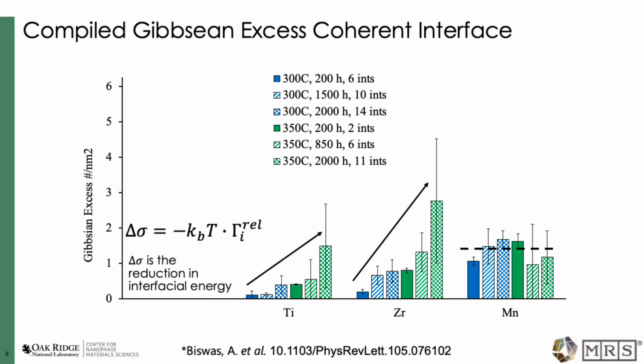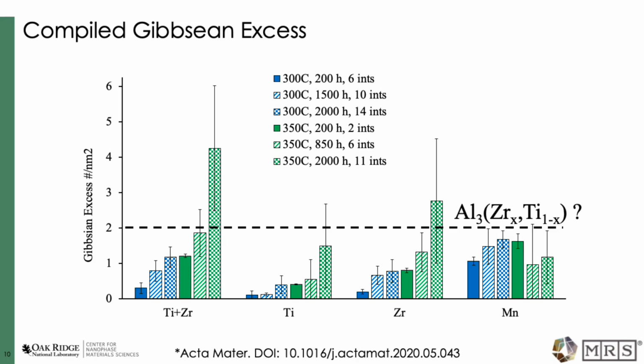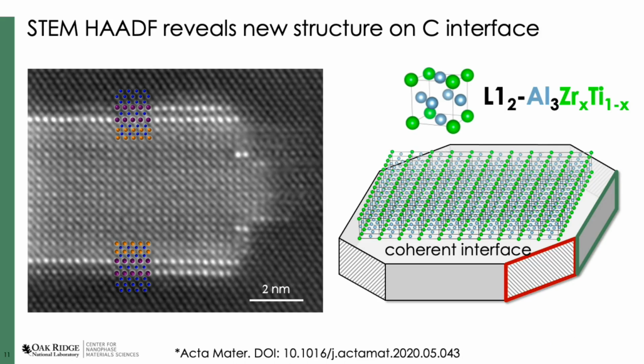As titanium and zirconium continue to segregate to the theta prime coherent interfaces, the interfacial energy continues to reduce. Another thing to note is that titanium and zirconium are L12 formers, and about one plane of L12 structure is about 2 excess atoms per nanometer squared. STEM HAADF imaging reveals that there is an L12 structure at the coherent theta prime interface.